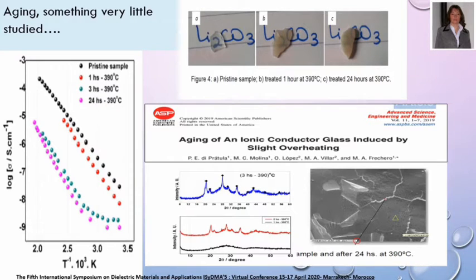We found that after a few hours, some crystallization appears, as you can see in the pictures on top. Also, some cracks on the surface, as you can see in the pictures above. Then, its structure stability is only affected if the overheating is near its Tg. Also, its conductivity diminishes over the time of overheating.